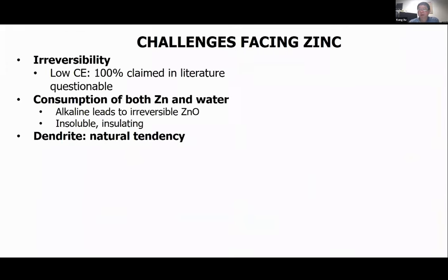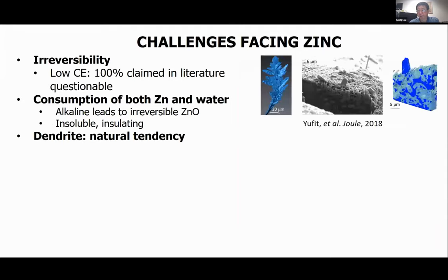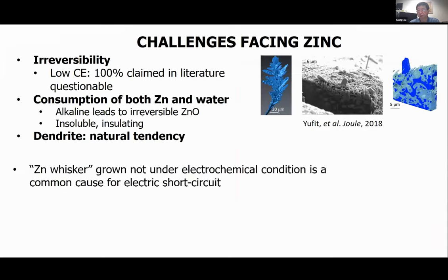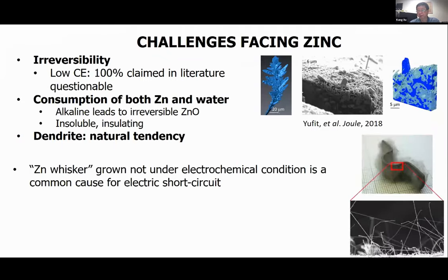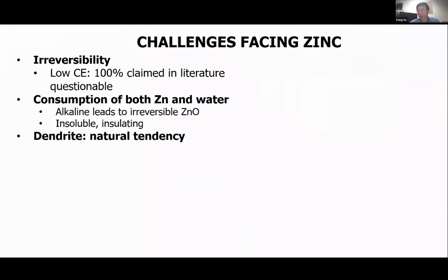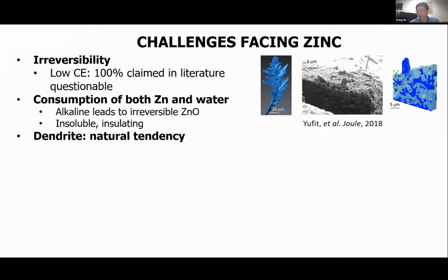So the challenge that the zinc metal anode is facing is very similar to lithium. Actually, it's the same challenge that all metal anodes face, which is dendrites. Because when you electrochemically crystallize such things from electrolyte, there's always uneven growth. And this uneven growth happens under electrochemical conditions, as you can see that zinc grows dendrites in a very similar way to its lithium cousin.